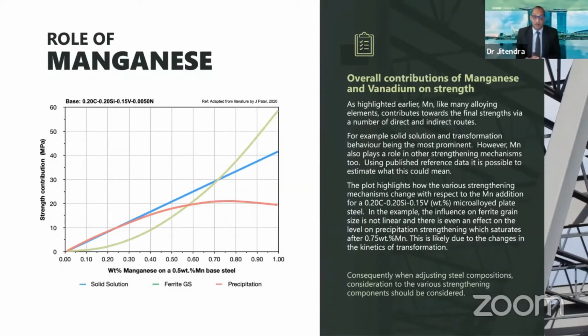This graph shows, for a vanadium-based plate steel, the precipitation strengthening here in red. In this steel, the vanadium content is 0.15, so very high levels. But as you can see, there's a saturation point as we go to higher manganese content on a base composition of 0.5. So at about 1.2% manganese here, at that 0.7 here on the graph, we can see that a saturation limit is reached, and that is due to this adjustment in the transformation, the depression of the Ar3. So we have to bear in mind all of these secondary factors when we start playing with the alloying content, and in particular the manganese content, that after a certain point, it also starts to limit how much precipitation strengthening you can get, here particularly for manganese due to the phase transformation itself.